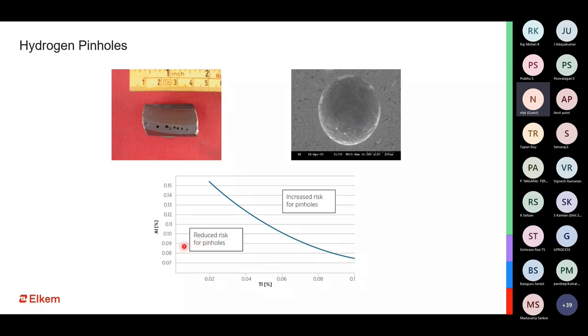Of course, when you have a lower percentage of aluminium and a lower percentage of titanium, the risk of hydrogen pinhole is much lesser compared to when you have higher aluminium and higher titanium in the system. So a control on titanium, more importantly, and a control on aluminium is important to make sure that we have good control on the hydrogen pinhole.